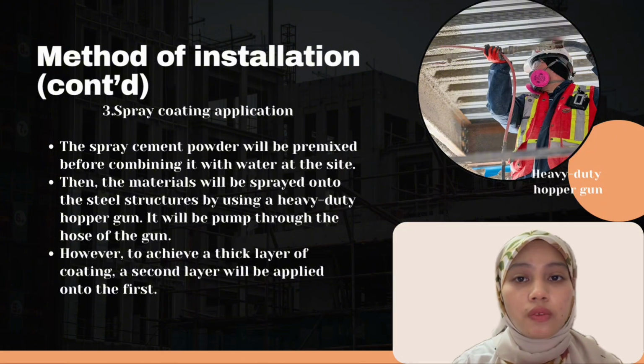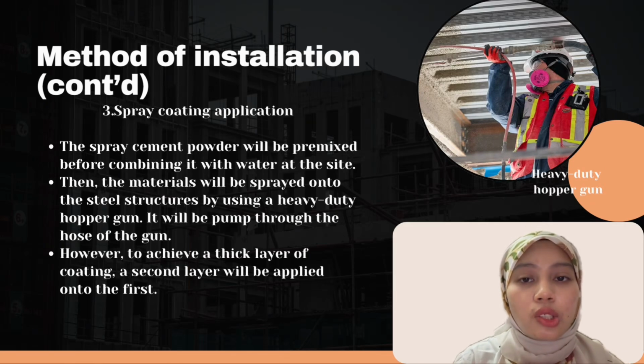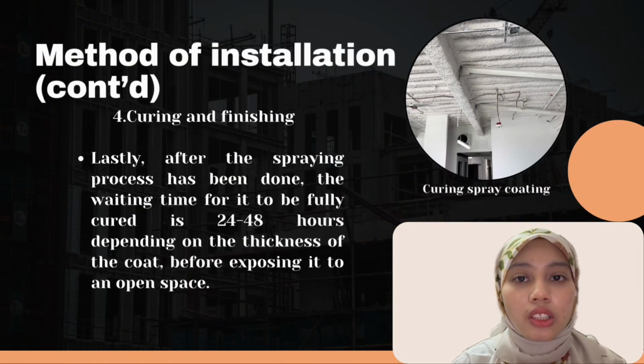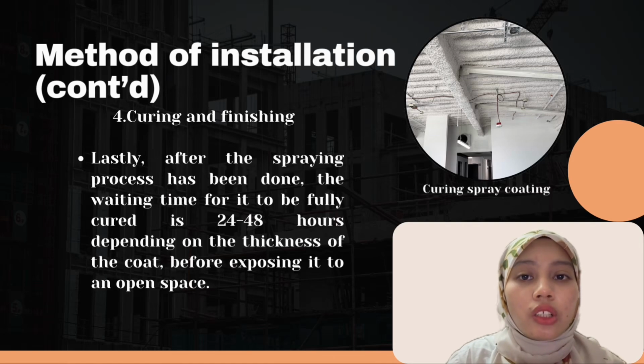However, to achieve a thick layer of the coat, the second layer will be applied after the first layer has dried. We have to wait for the first layer to dry and set before applying the second layer, so that sloughing of heavy material can be prevented. The last step of the method of installation is curing and finishing. After the spraying process has been done, the waiting time for it to fully cure takes about 24 to 48 hours before exposing it to an open space.